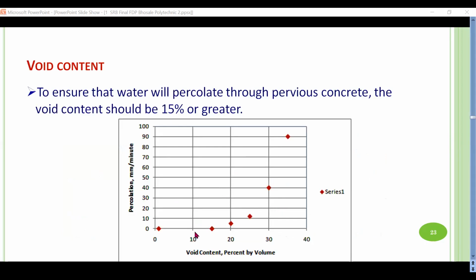So you can see here a graph, percolation in mm per minute against void contents in percentage by volume of the total concrete. As the void content increases from 10 to 20, 30 or 40, the rate of percolation increases. This point is approximately 15% void content. The meaning is, if the void contents are less than 15% for a concrete, the percolation will be almost zero. So voids are present, but they are not interconnected. It is just like a honeycombed concrete.